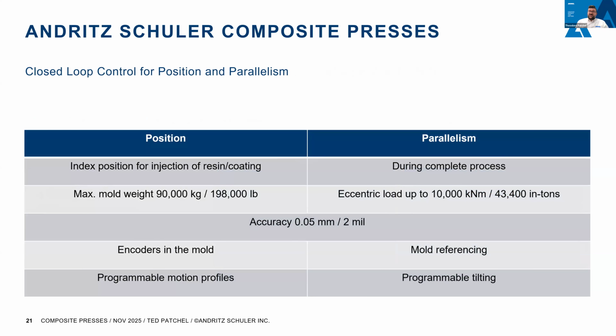These systems create a closed loop of control for both position as well as parallelism. The positional indexing is done for the injection of resin or coating through encoders in the mold that are programmable. They're capable of mold weights of up to 90 metric tons with an accuracy of 0.05 millimeters. Our parallelism controls are operated during the complete process through mold referencing and programmable tilting. Our parallelism controls are capable of withstanding eccentric loads up to 10,000 kilonewton meters with an accuracy up to 2 mil.